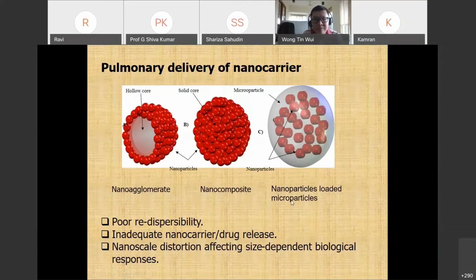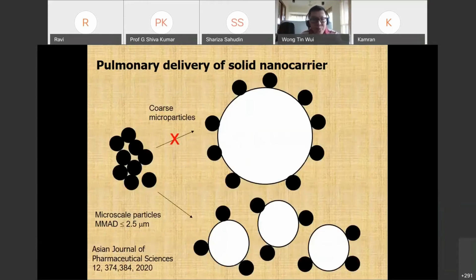Now, all these nanoparticles experience poor redispersibility. Hence, we may not get any nanoparticle in the deep and peripheral lung. And a lot of times, due to the polymeric substances encapsulating the nanoparticles, the nanoparticle or even the drugs cannot be released for the intended action. And worse still, in the process of making microparticles, your solvent and polymeric material may actually distort the size of the nanoparticles. This is highly unfavorable because uptake of nanoparticles by cancer or even by normal cells depends on the size features. Right. So on this note, we hypothesize a possible way to deliver the nanoparticles in a better capacity.